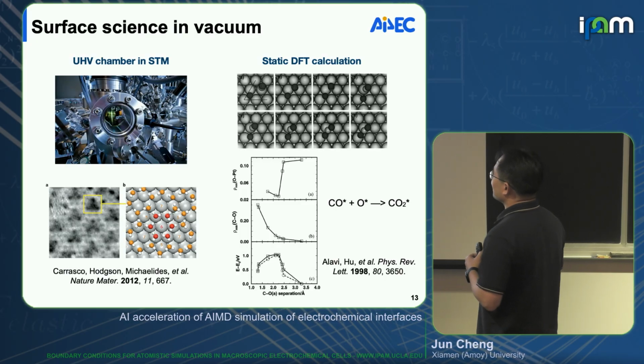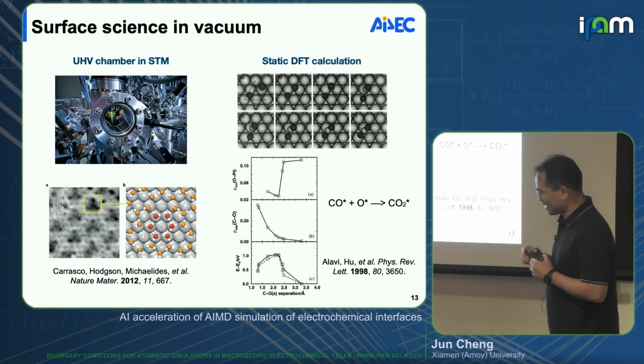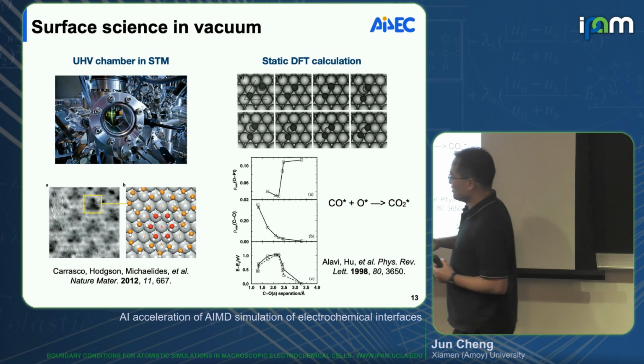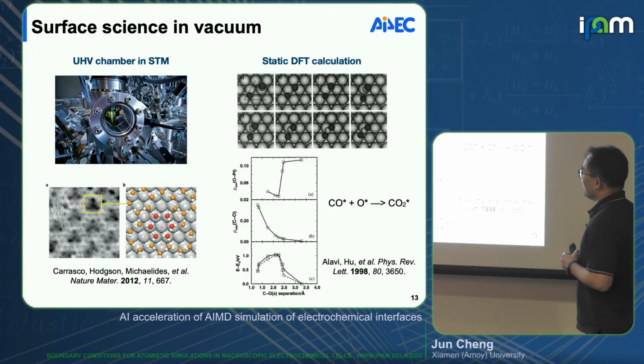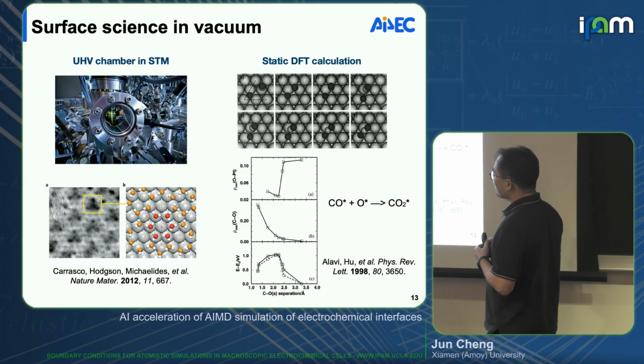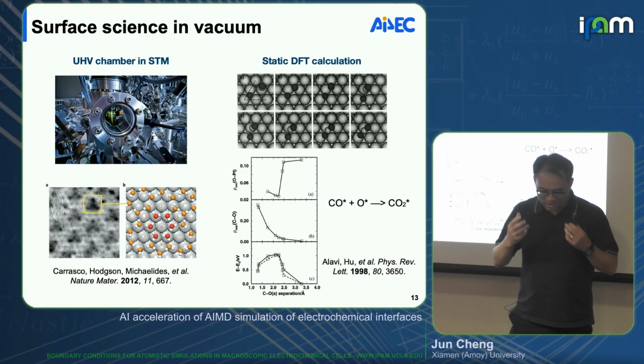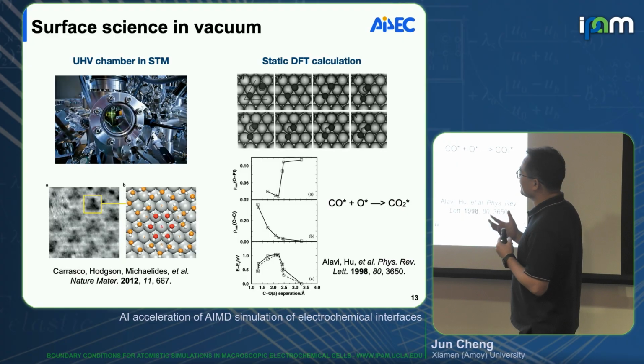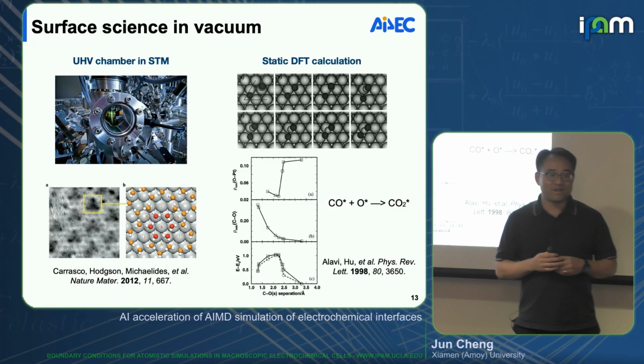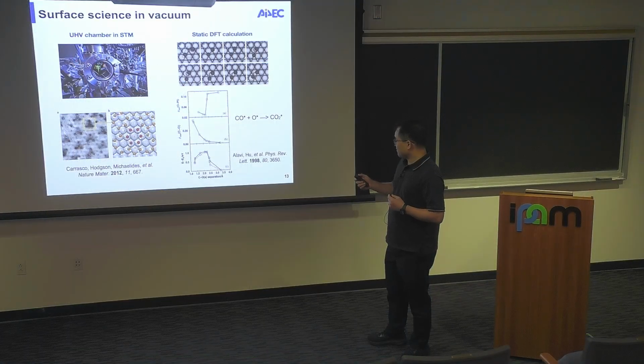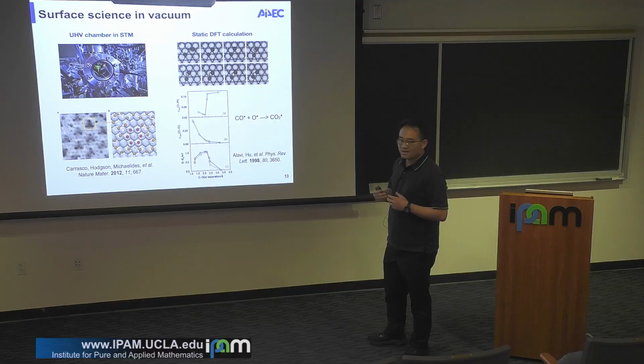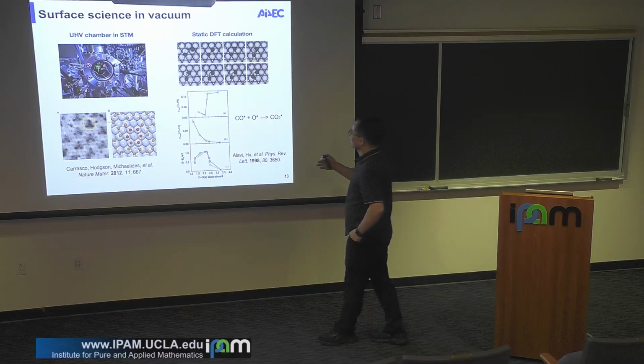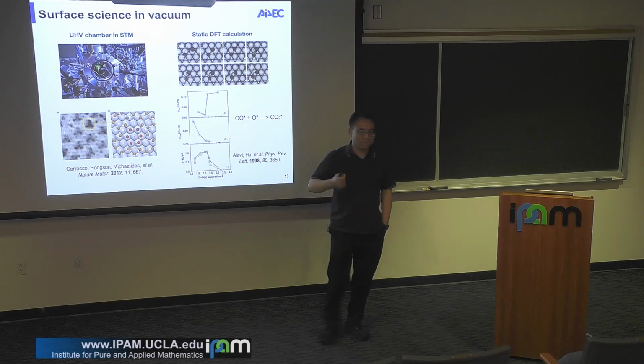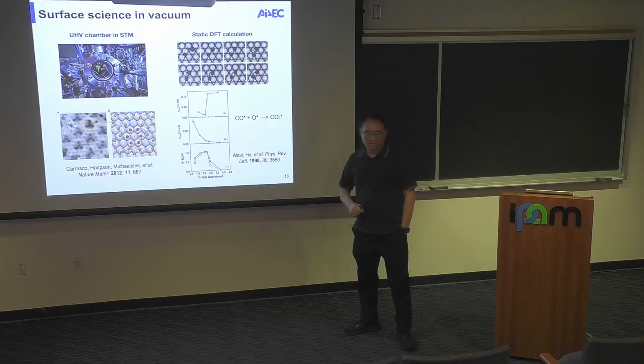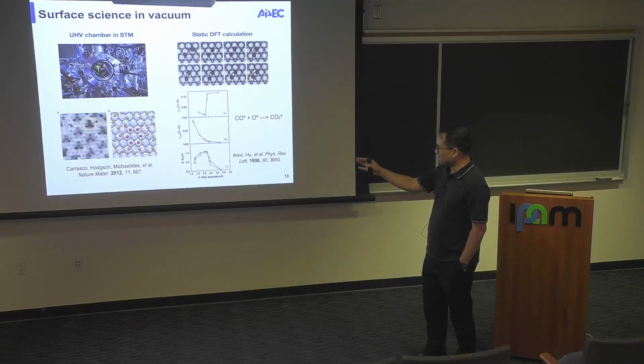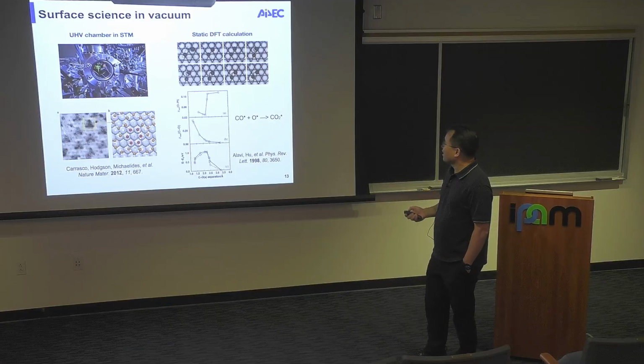Another example I quickly show is really from my PhD. I did surface catalysis as well, like Axel working on this for many years. It is a surface science approach. Experimentally, in order to really see the adsorbate at high precision, you need to do that at ultra high vacuum condition and at very low temperature. And the same, the DFT calculation has a really good correspondence, right? We do the optimization, we locate the most stable structure at 0 Kelvin, and then we can even search for the transition state. That's all nice, very good correspondence between theory and experiment.